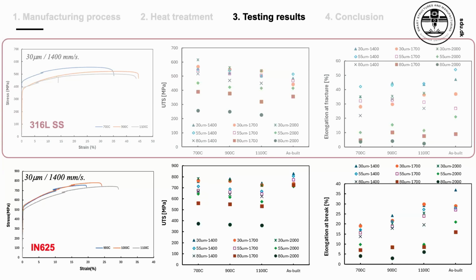Even the literature, forget the heat treatment, even just as-built, it should deliver the worst mechanical properties, ductility and also UTS, as we can see here as well. So the trend here follows the as-built even for a single case, and so on from 700 to 1100 again is because of the recrystallization, formation of the grains, like the size of the grains, and also formation of the grain boundaries, bigger grains and then smaller grain boundaries, and also in some cases more room for dislocations to move better, so better ductility in that case.